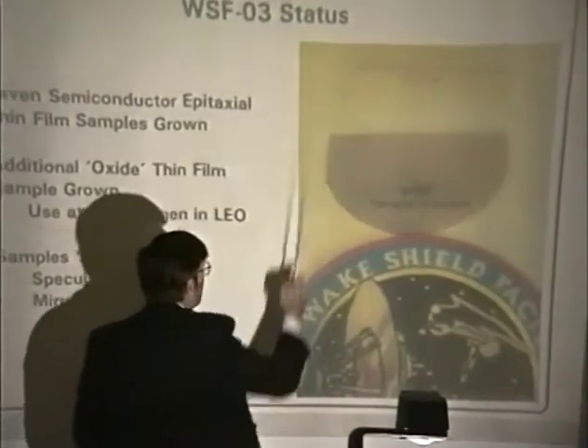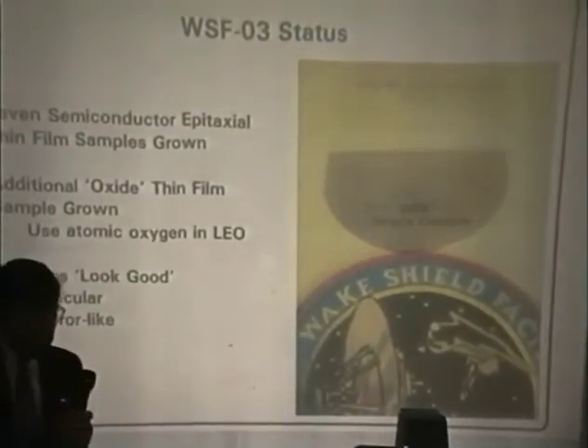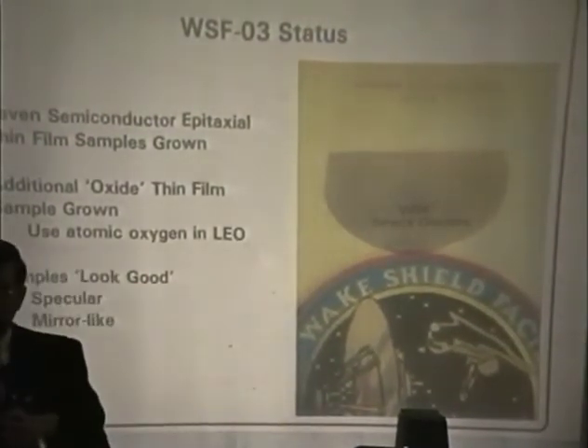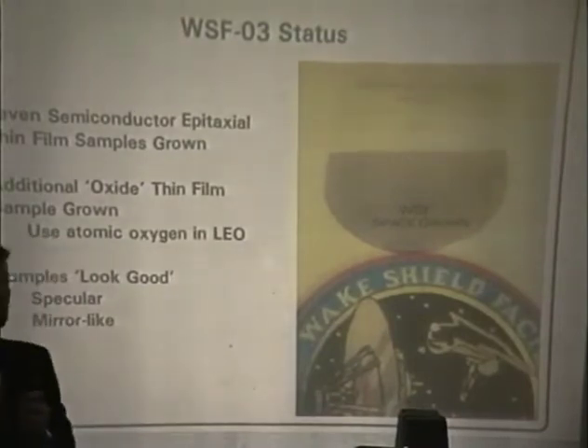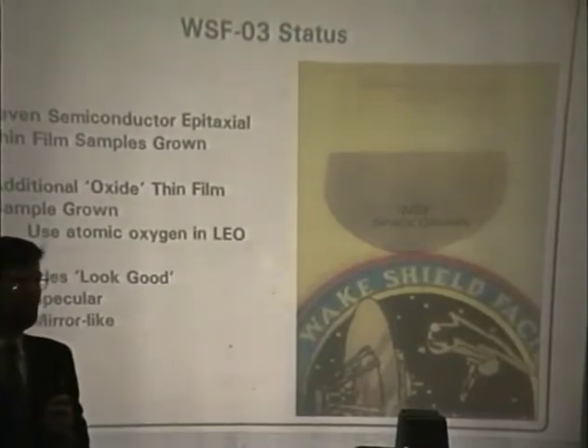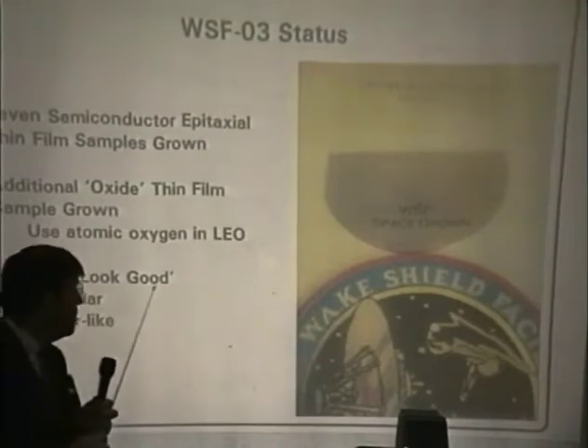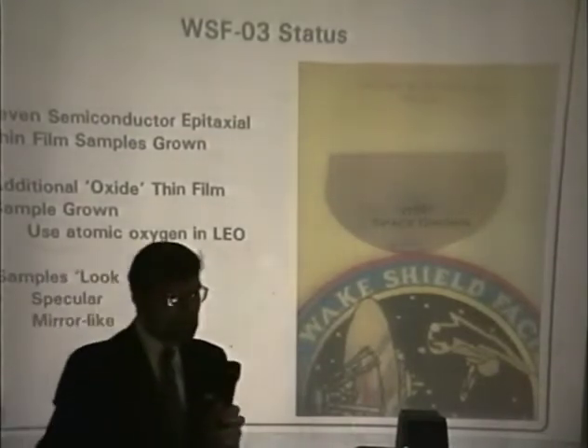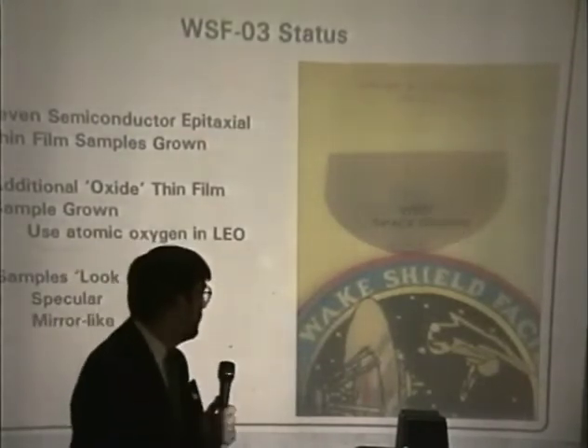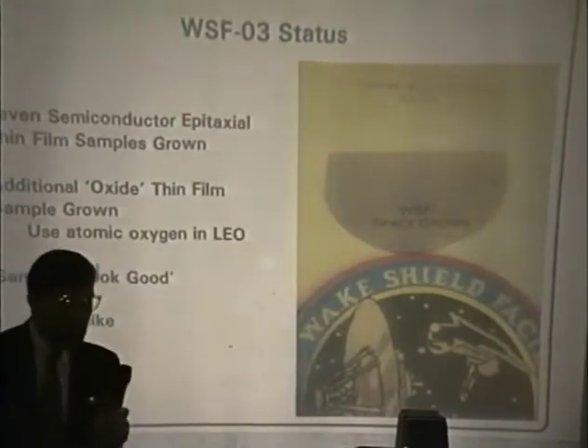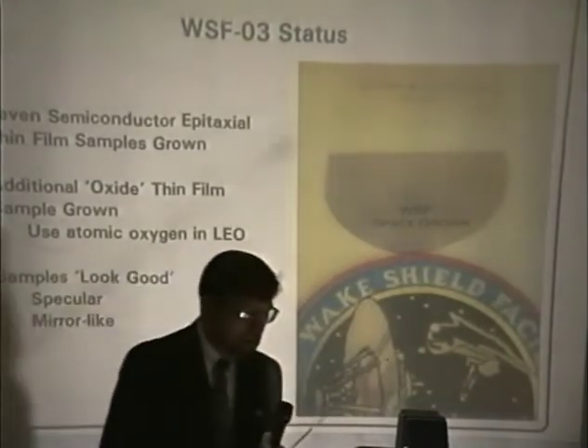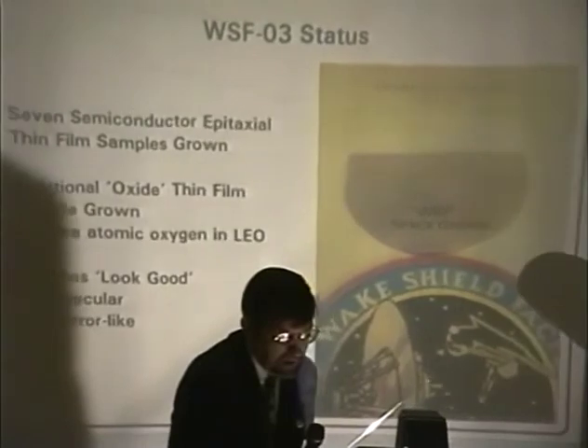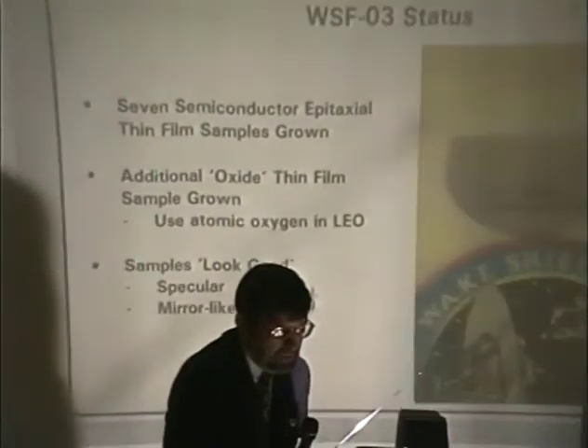The Wake Shield 3 wafers, here is half a wafer that we grew, and that's just a reflection of a typing up there. One of the first signs of a good quality growth is a very specular surface. You grew a thin film that is very smooth, and smooth at the atomic level, although the specularity at the wavelength of light here doesn't show that. We've seen, however, from further analysis that in fact we have extremely specular surfaces, therefore high quality thin film growth.